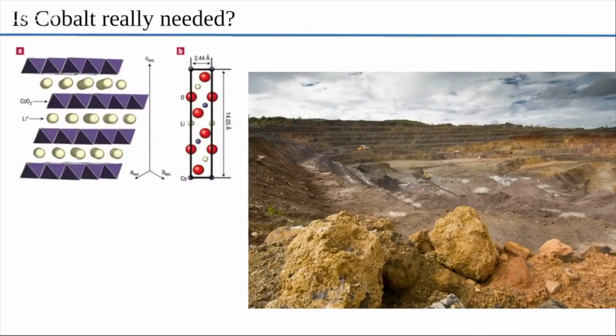One of the questions that Tesla has been working on is, is cobalt really needed? What we see in this picture is a mine in Congo, and there are some really heartbreaking pictures on the internet. You can check, but basically cobalt comes from mines like this, and the cobalt oxide or the cathode structure looks like this. You have layers of oxygen, cobalt, oxygen, and then there's a layer of lithium. So the lithium goes in here, there's an oxygen on this end, in the middle you have cobalt, then you have oxygen on the other end, then cobalt. It goes on like this.